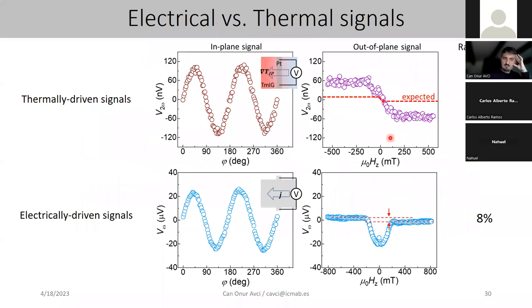Okay, so you might wonder, there was an anomalous Hall effect signal, why not its thermal counterpart? To find out if the thermal counterpart could explain that, we did some experiments comparing two different devices that are very similar in geometry and characteristics, next to each other. One is driven by purely electrical currents, and the other by purely thermal gradients. In-plane, we have these two signals that are basically the electrical and thermal counterparts. But for the out-of-plane signal, in the electrically driven case we have a very small signal, while in the thermally driven case we have a large signal.